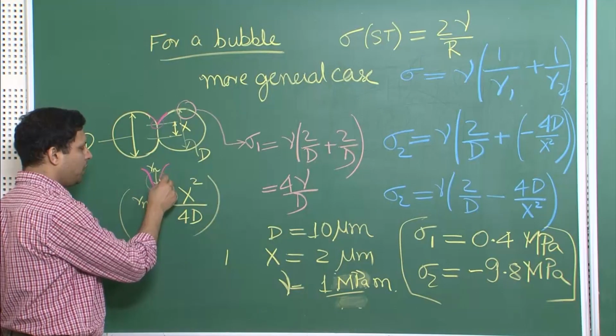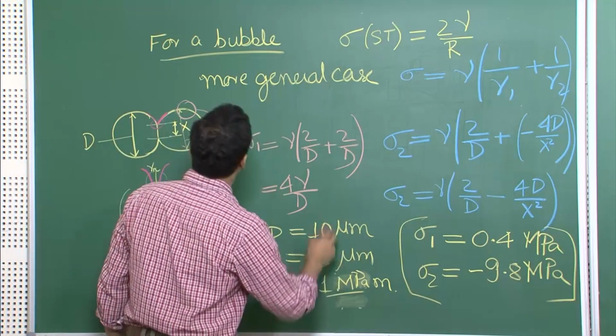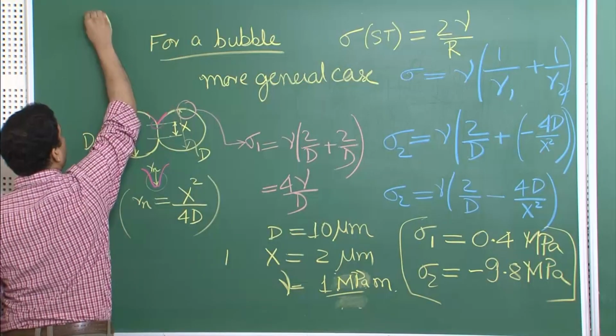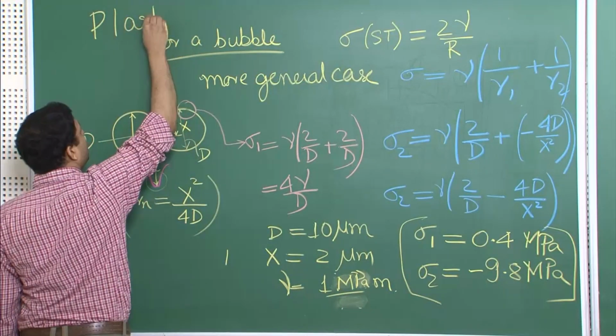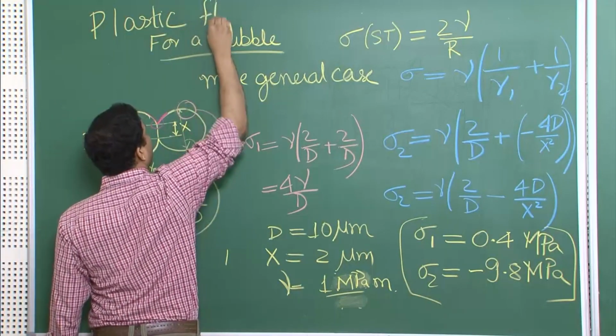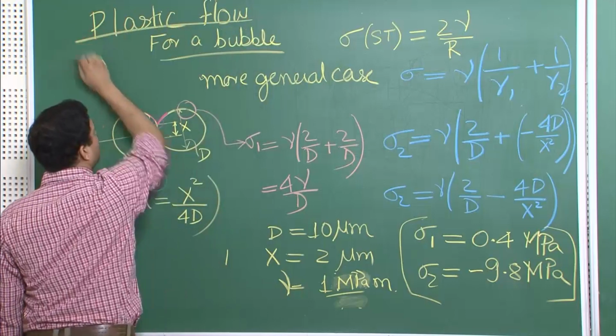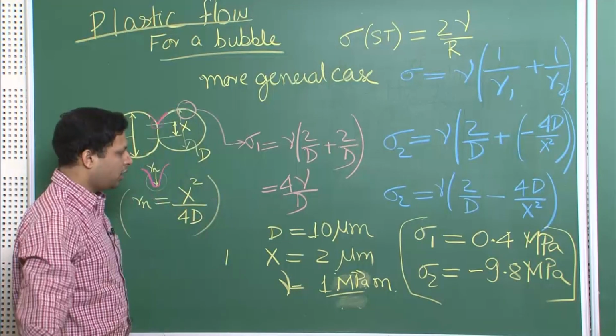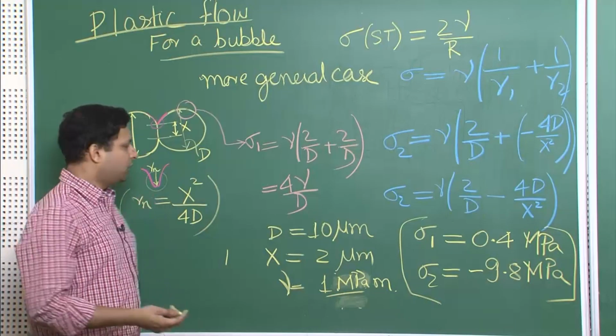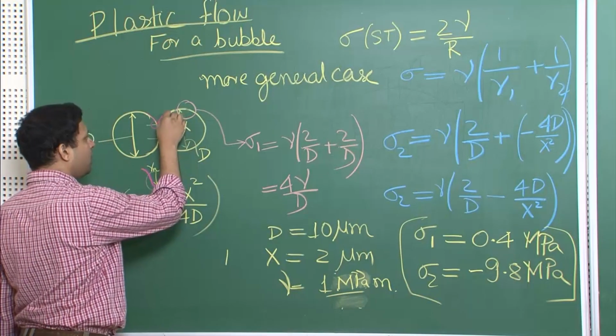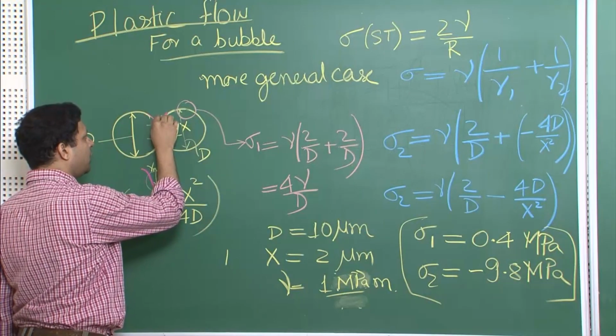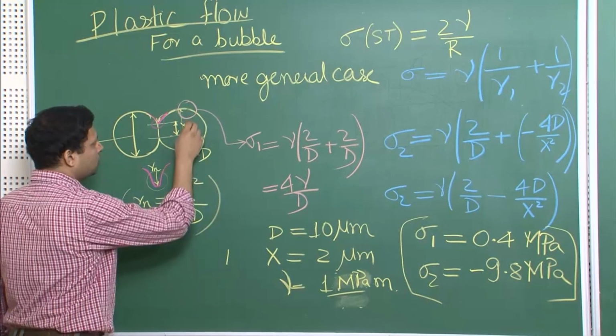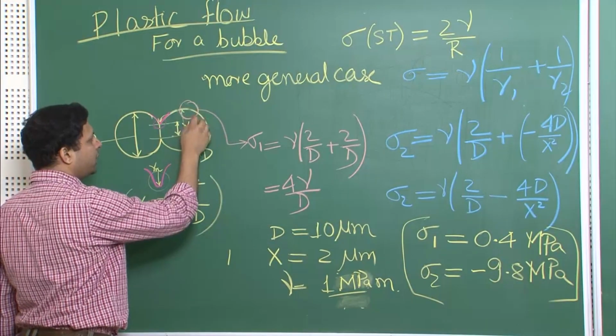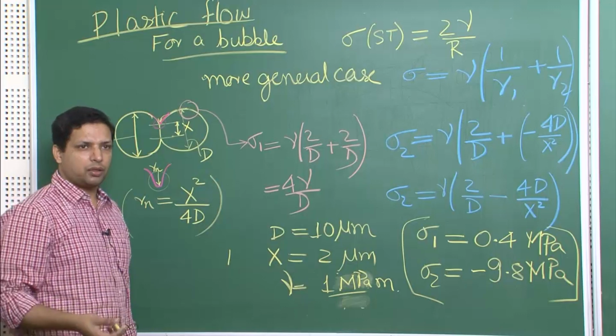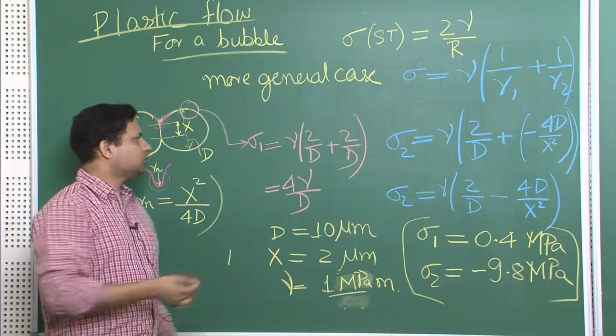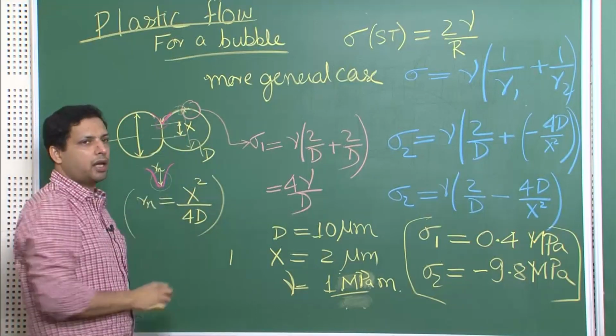That would mean that there will be large plastic flow. So, what we will get over here is what we wanted to derive for this kinetics, which is plastic flow. So, this is what we wanted to emphasize, that because of the surface tension you will have plastic flow, and therefore, material will flow from near the neck region into this region. And another thing is that there is a big gradient from here to over here. So, it is this gradient that is driving the material from over here into the neck region.